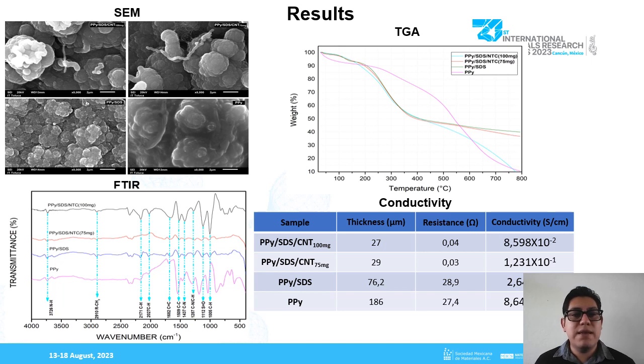Finally, the conductivity analysis shows that a polypyrrole film has higher resistance, resulting in lower conductivity. A polypyrrole with SDS and with 75 milligrams of carbon nanotubes film exhibits better conductivity compared to the others, with a value of 1.231 times 10 to the power of negative 1.